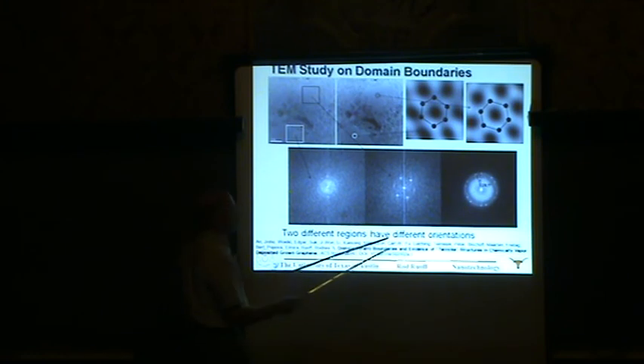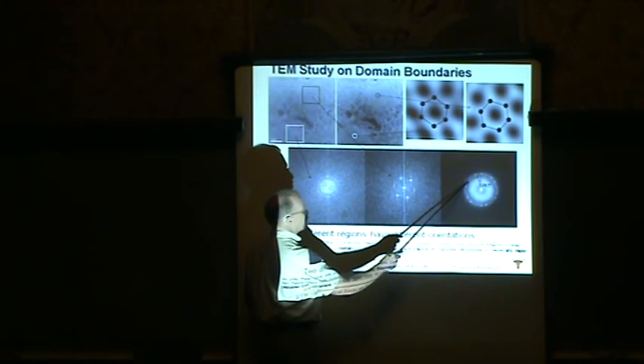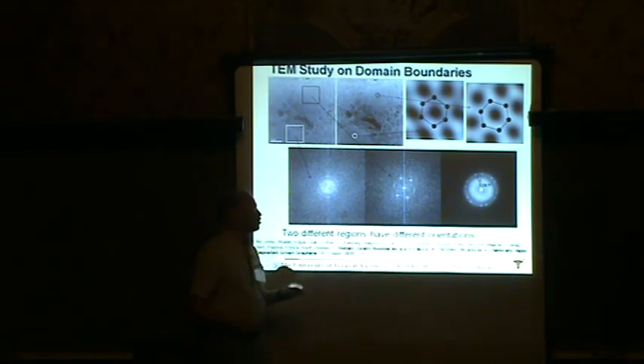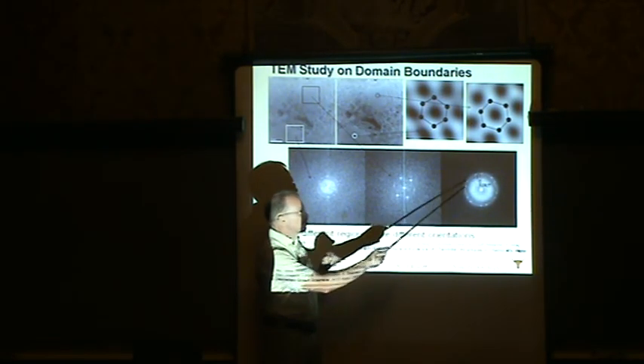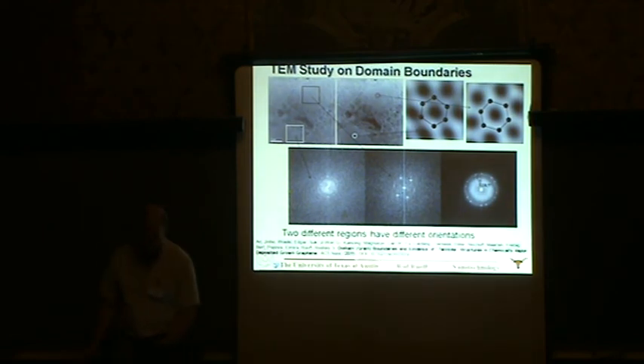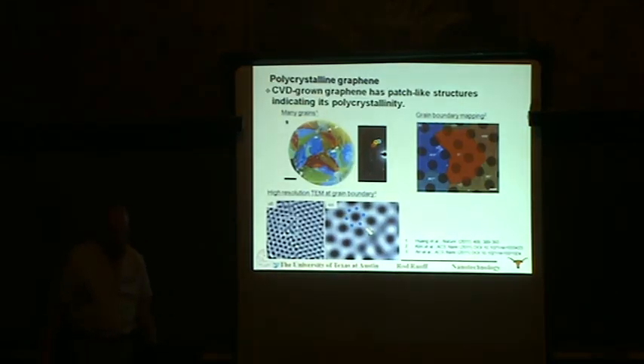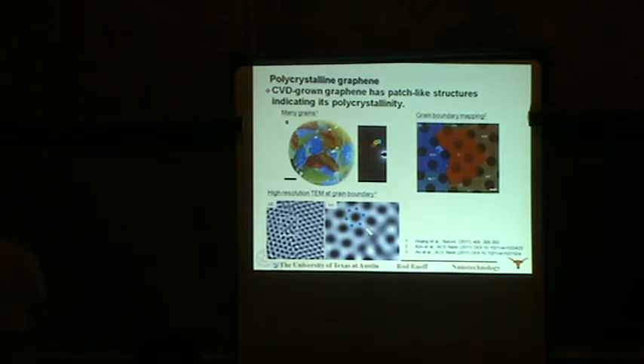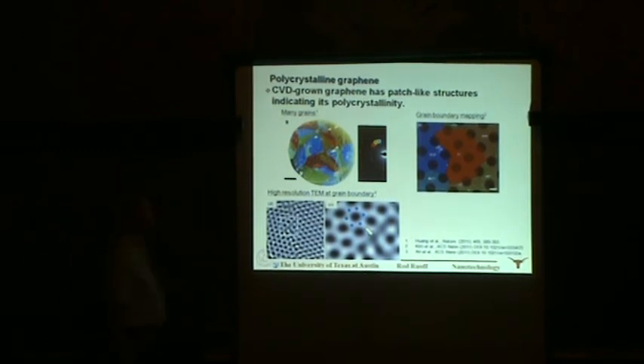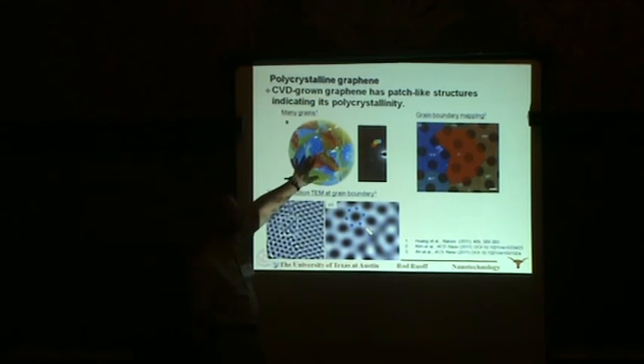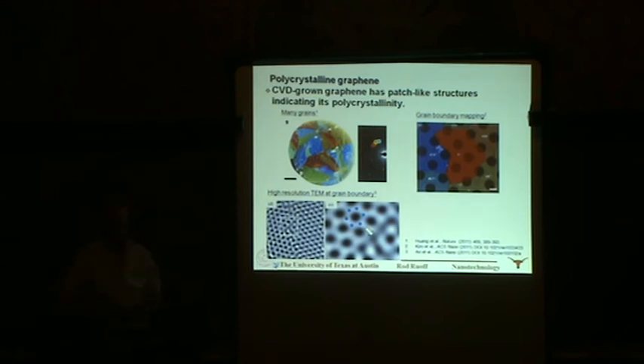This is simply showing that, indeed, in the region of the grain boundary, you'll have two sets of hexagonal spots showing that you're overlapping two grains that are misoriented by 18.5 degrees. This is a different example from the Cornell group, where they showed that because they had a very small grain size, they could use simple dark field imaging and map the grains very quickly and color code them, so they ended up with these sorts of beautiful pictures. But this was a consequence of having quite small grains. And so then you can see all the grains quickly through this dark field.